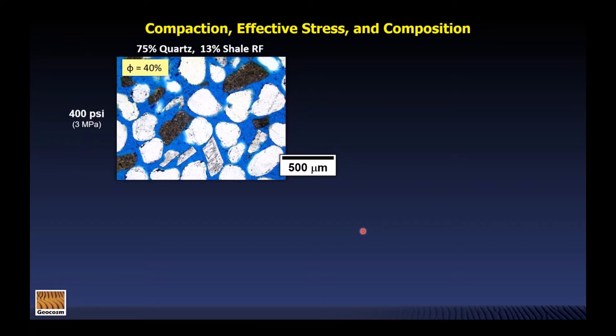And so this is an experiment where we had about three quarters of the grains made up of natural quartz grains. Those are these well-rounded white grains here. And the remaining grains were evenly divided between these shale rock fragments and these angular feldspar grains. Now, this is a thin section of the pack that we made in the lab, and we subjected it to very low effective stress, just about 3 megapascals.